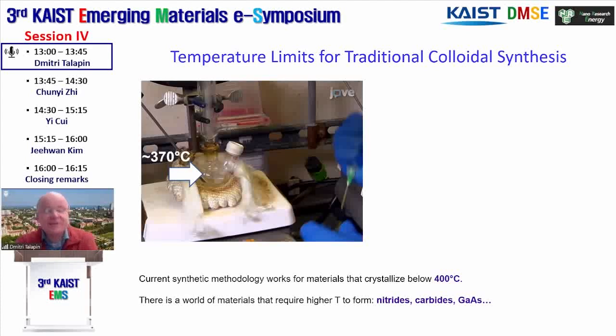Okay, with this, I would like to finish the part of the discussion on colloidal ALD and precision, with a word of caution. I probably painted a very optimistic picture that we can control synthesis of nanocrystals down to atomic precision and so on and so on. And yes, we can do it for a very small subset of materials that can be efficiently nucleated and grown at temperatures around 300 degrees Celsius or so. Because in that reaction, in that video that I have shown you a few minutes ago, the solution in the flask was preheated to 370 degrees Celsius. And that's arguably the highest temperature we can really push the solvents to.